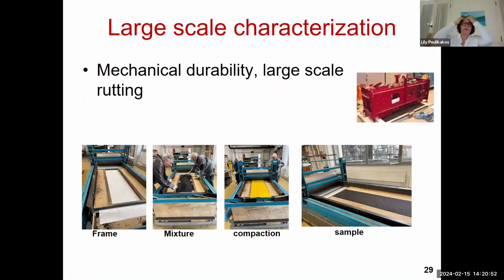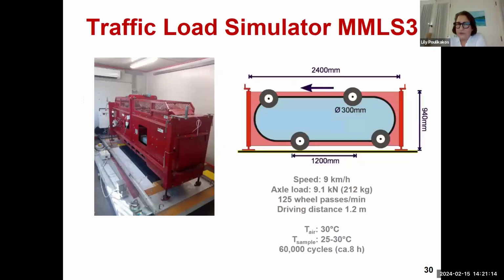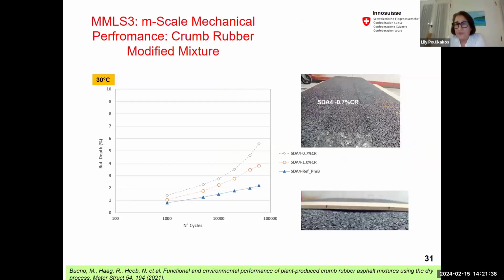Now I'm moving on to the larger scale characterization methods. Here I'm showing you how we prepare the samples. These are large samples, large slabs that are produced using a frame and using a roller compactor. And you see that we are using a traffic simulator to test these. There are 4 wheels for this traffic simulator. It goes at a speed of 9 kilometers an hour and an axle load of 9.1 kilonewtons. And these tests were performed at 30 degrees. So basically we are testing for rutting, but on larger slabs.